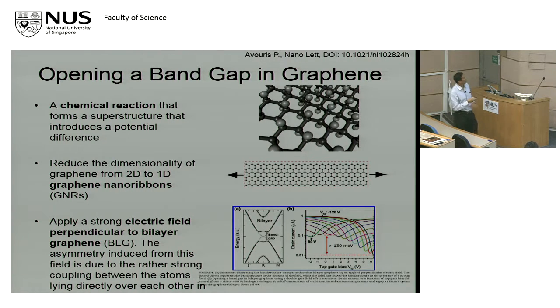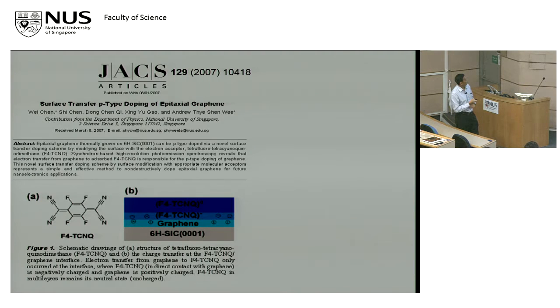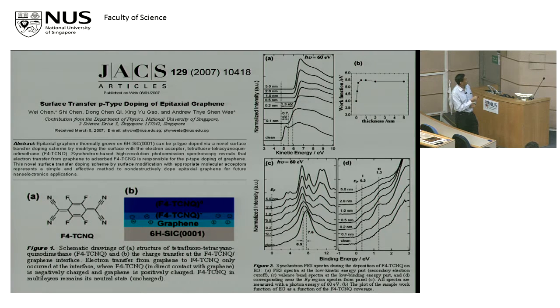So the first chemical reaction, in fact, what Chen Wei did, this was when he was LKY postdoc, since we were working on molecules and surfaces already, right? It was easy for us to do this. He put F4TCNQ, a strongly electron withdrawing molecule, on the epitaxial graphene that we were already growing, and it withdrew charge. So this became hole doped, and it also opened a small band gap, okay, but a very small one.